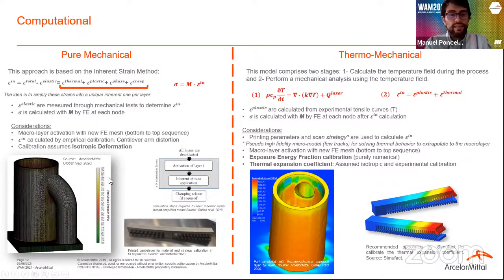As it was previously said, at the end of the day, these models have a degree of simplification, because performing high fidelity simulations of this kind of sample would last a lot of days and with high computational cost, and it's not affordable. So in this case, there is a macro layer activation. Initially, all layers are deactivated, and then there is a successive macro layer activation from the bottom to the top, and the final part is reached. And the stresses are calculated by finite element at each node of the mesh.